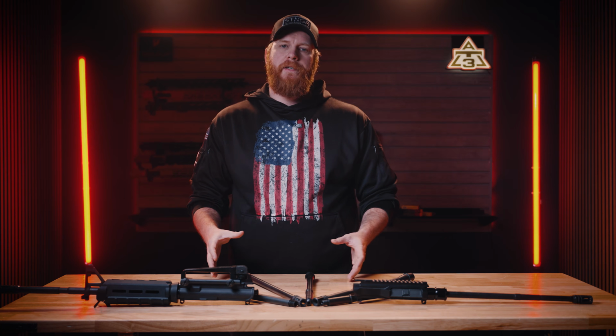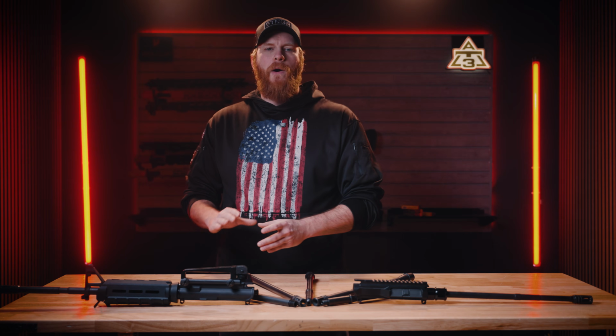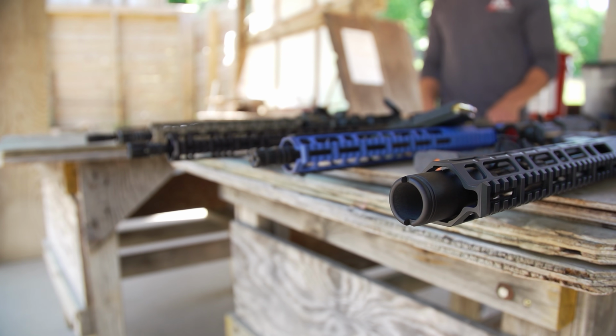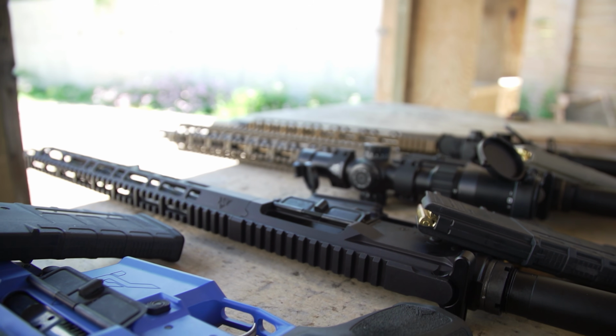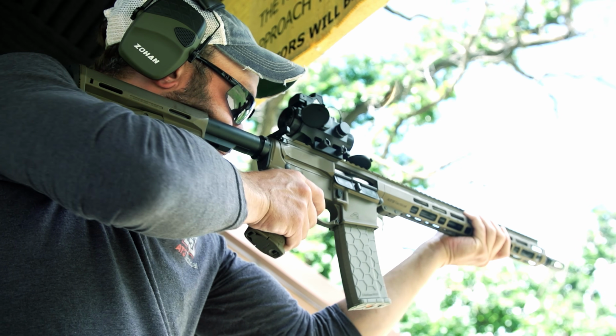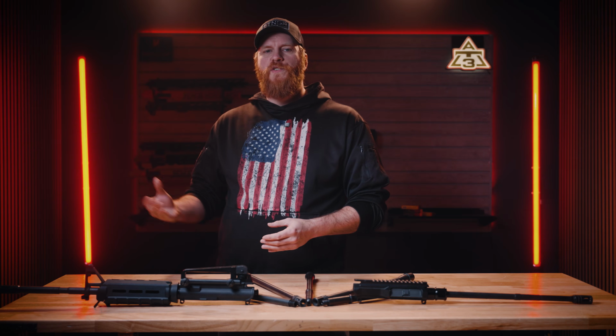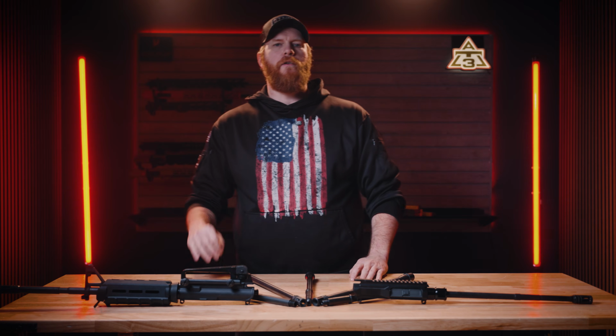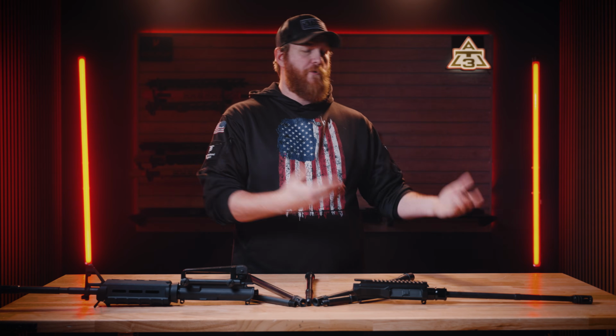Now, 4140 offers decent tensile strength, good durability for non-abusive use, and it pairs well with your affordable finishes like nitrate and phosphate. That cost saving, however, comes with the drawbacks of having a slightly less heat-resistant material that's not as long-lasting as the competition under heavy use. It's also not as inherently accurate or corrosion resistant as something like 416R stainless, unless it has extra treatments, and those extra treatments are often going to push the barrel cost up just a little bit, in which case it might be easier just to go with a 4150.